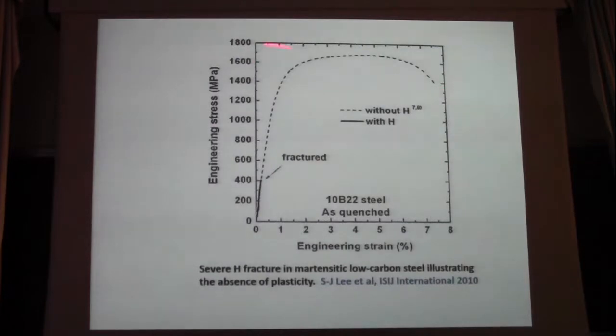Here's a fracture here. Without hydrogen, you get this tremendous strain hardening, post-uniform deformation, etc. With hydrogen, you get a fracture in the elastic portion of the engineering stress strain curve. Now, other types of fracture go beyond yielding, but never quite reach the ultimate tensile strength. So, the different fracture mechanisms can have different degrees of severity.